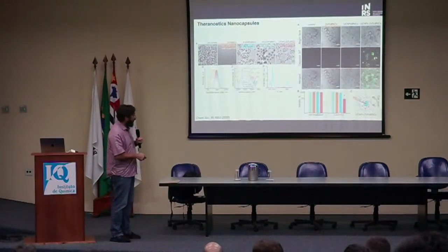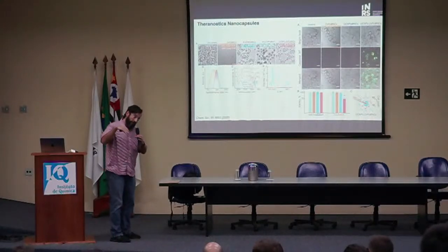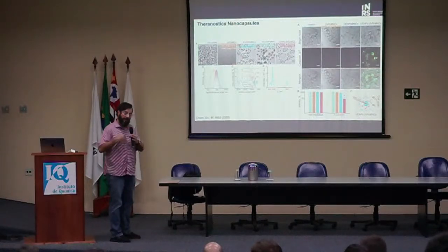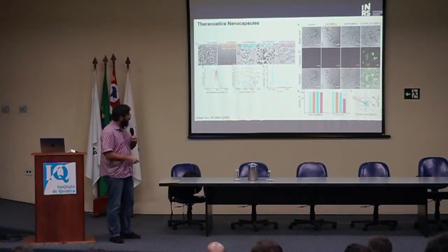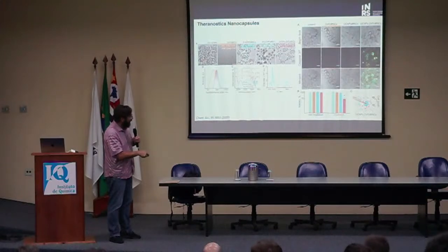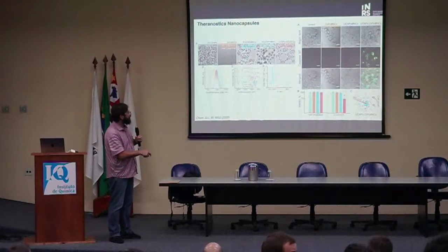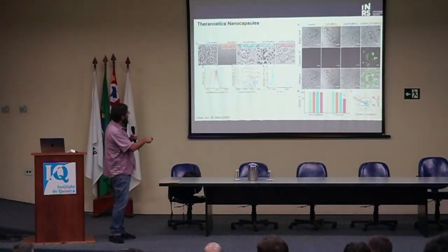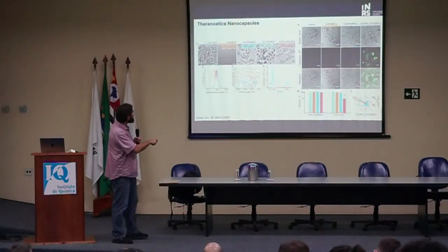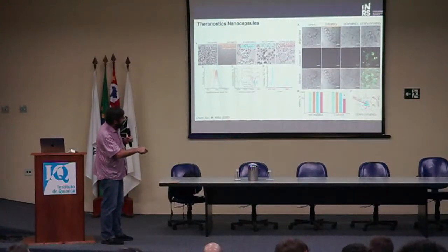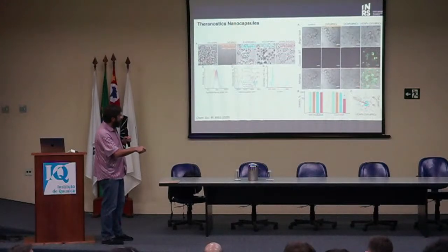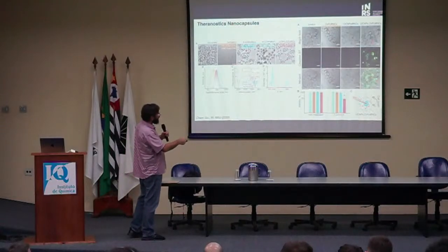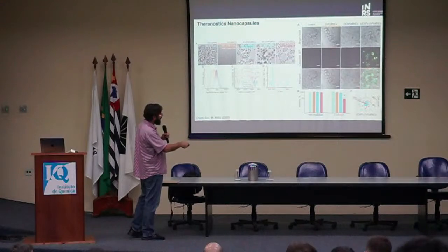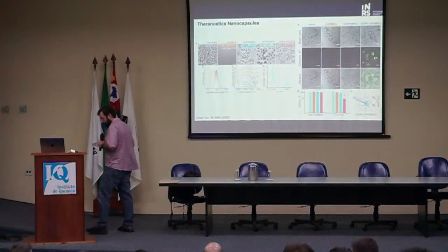So, of course, what we want to do is use our nanoparticles that can convert near-infrared light that penetrates the skin to higher energies, and use them as sort of a transducer, as an intermediate, if you want. So we excite the nanoparticle, it generates the visible light inside the body, and then that light is absorbed by the photosensitizer, which then generates the reactive oxygen. So all that to say, the important data is right here. This is the actual structure we made. You can't really see it, but anyway, this is the structure right here. And this is the important data here. This is caspase. The cells are stained with a dye that detects cell apoptosis, so when a cell dies. And you can see that when we have our nanoparticles with the dye in the nanocapsule, pretty much all the cells die. And that was an important finding.